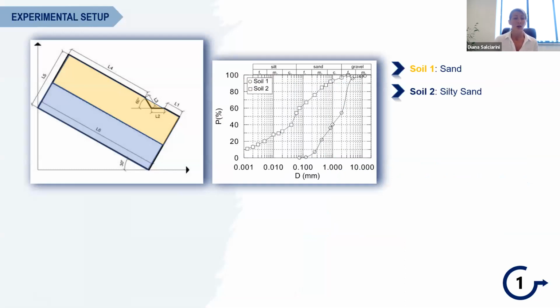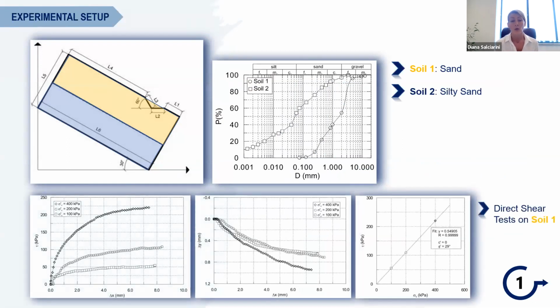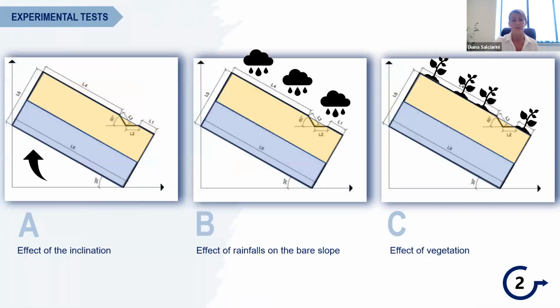This is a sketch of the experimental setup. The box is filled with 2 layers of soil. The upper soil is basically a sandy soil. The lower layer is a silty sand. Here you can see in the graph the grain size distribution curves for the soils. And we performed some direct shear tests on the upper soil, and we identified the soil as a purely frictional soil with null cohesion and a friction angle equal to 29 degrees.